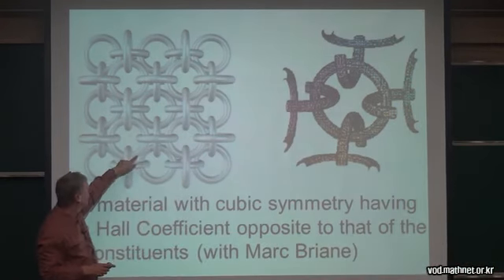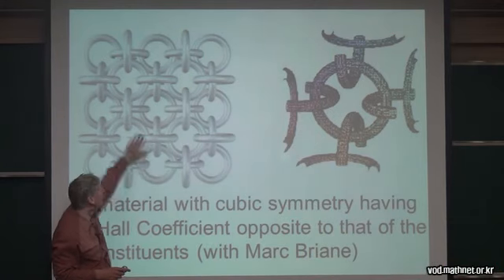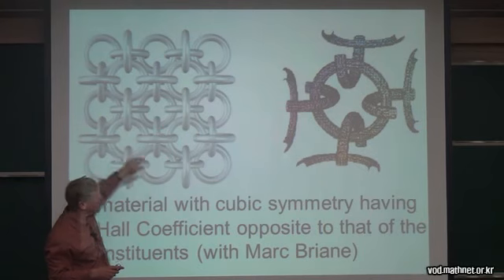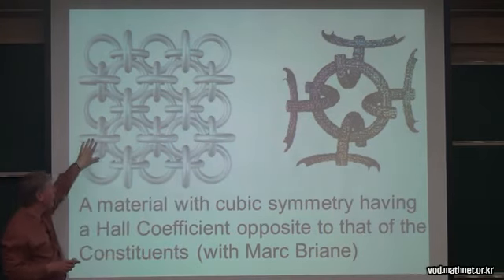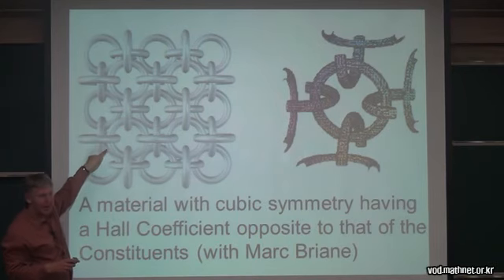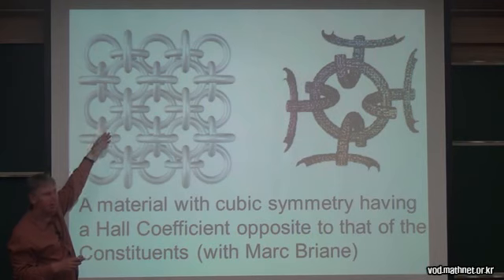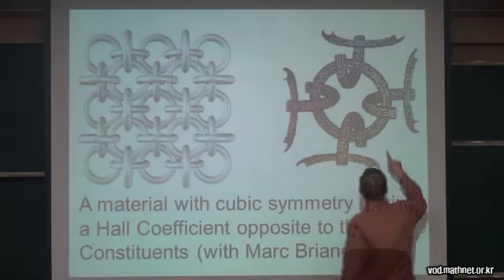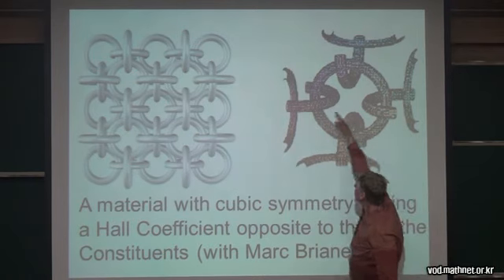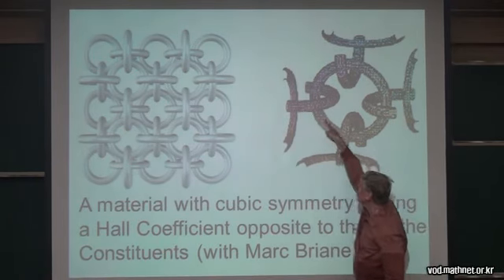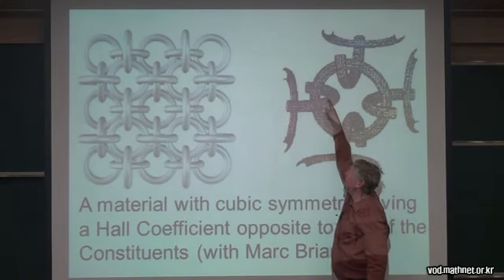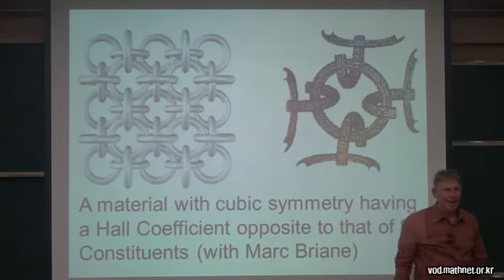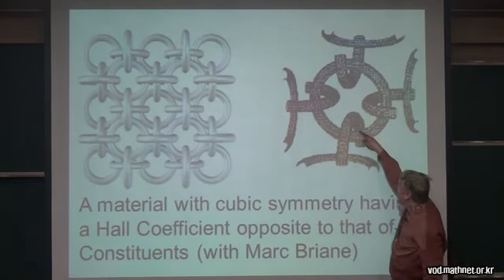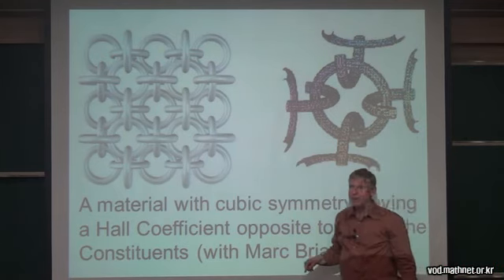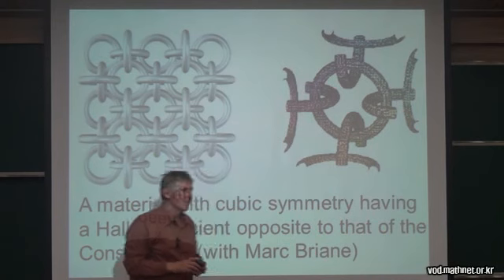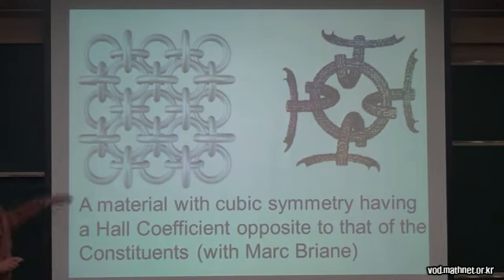And this is the first few layers of the three-dimensional geometry, but this is the period cell. And what you have here is highly conducting rings, with something with cubic symmetry, and in the gaps, if this has got higher electrical potential than this one here, or this has higher potential than this one here, then in the gaps, the electrical potential is in the opposite direction, actually. And so if I put my material with high Hall coefficient in these gaps, I'll actually end up with a composite which has got opposite Hall coefficient than is expected. And actually we're able to prove that rigorously.